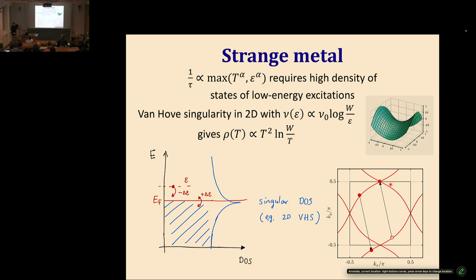Okay, and it turns out that this picture is still a little bit misleading. You actually also need multiple bands to see this extending down to the lowest temperatures. That has to do with the kinematics, with the particular kinematics of when the scattering process is available. But luckily, in the example that I'll show, all of these conditions are met. So you can have Umklapp scattering, you have multiple bands, and yeah.